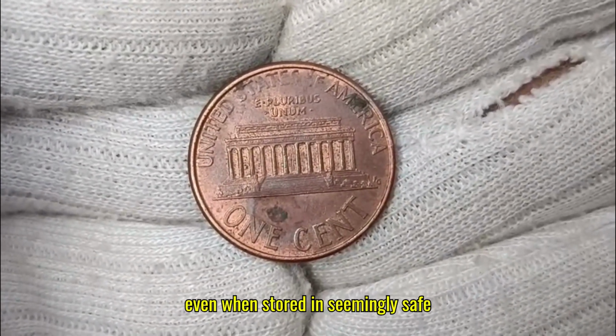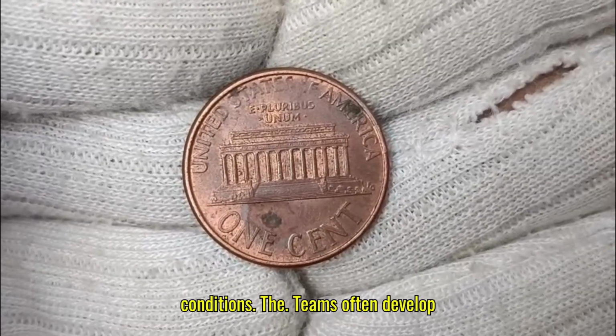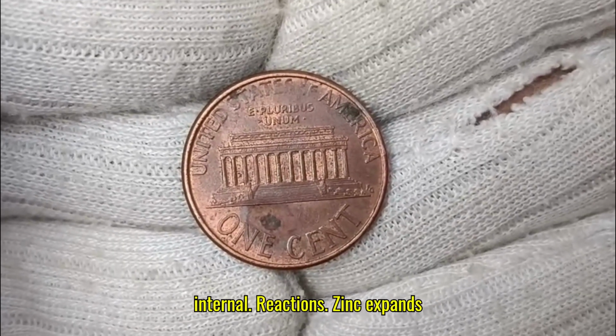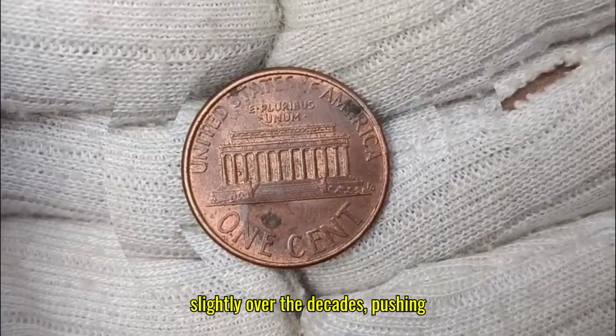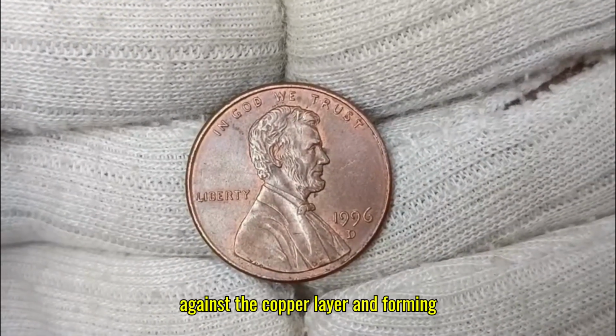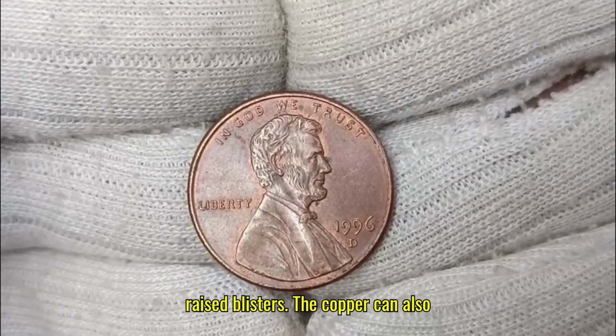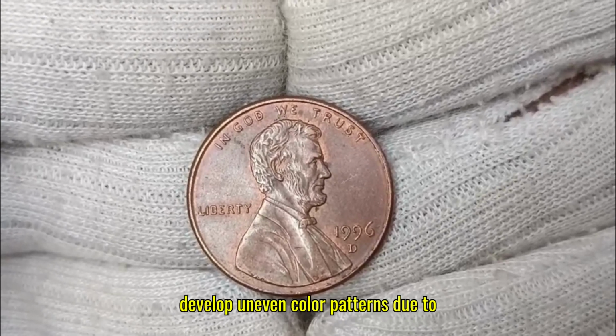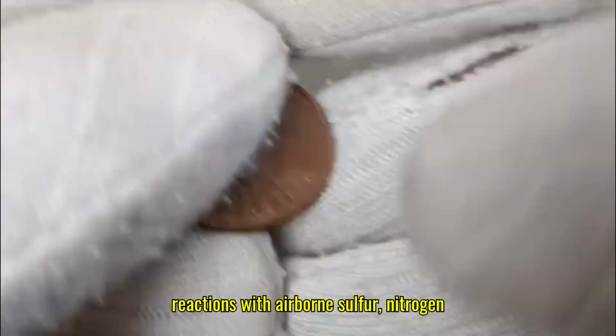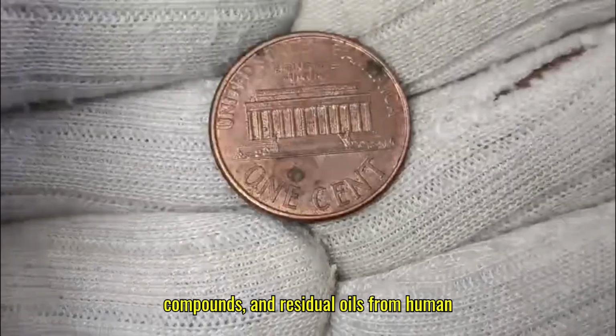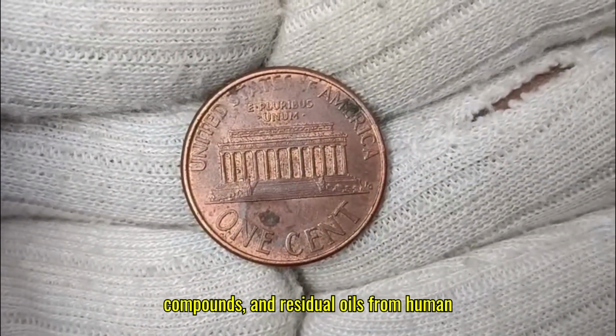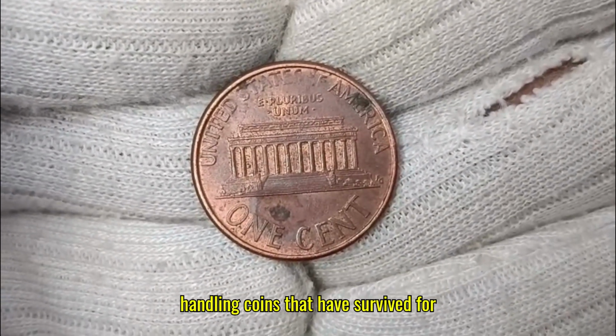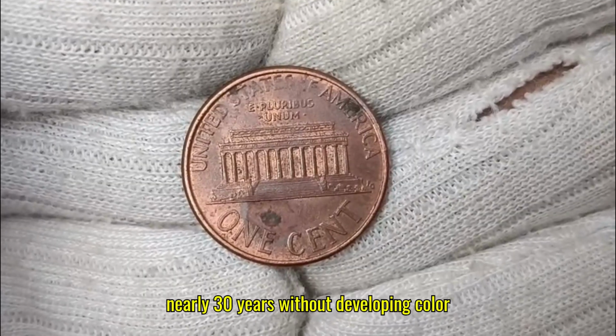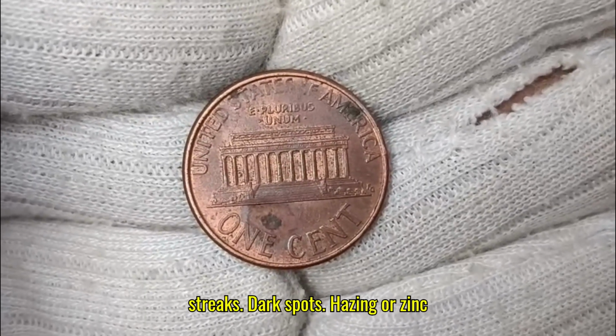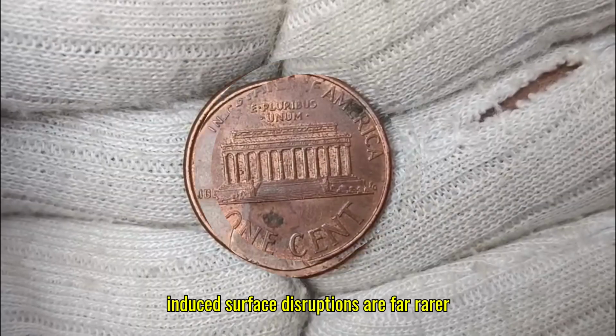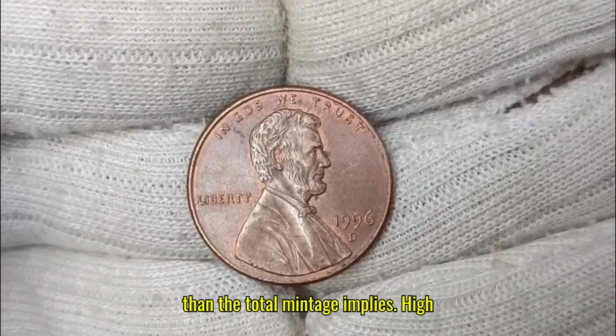Even when stored in seemingly safe conditions, these coins often develop internal reactions. Zinc expands slightly over the decades, pushing against the copper layer and forming raised blisters. The copper can also develop uneven color patterns due to reactions with airborne sulfur, nitrogen compounds, and residual oils from human handling. Coins that have survived for nearly 30 years without developing color streaks, dark spots, hazing, or zinc-induced surface disruptions are far rarer than the total mintage implies.